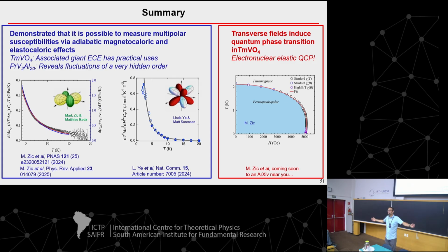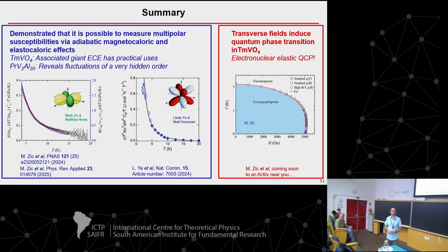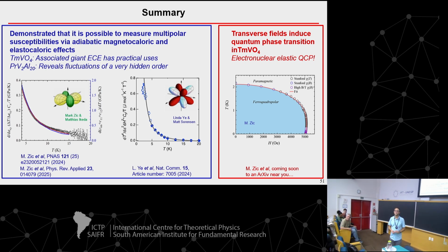Hey, Ian. There might be easier ways to do this, but I'm a neutron scatterer. If you start to polarize the nuclear spin, you will change the nuclear cross-section for neutron scattering. So you could look at diffraction peaks which had a large thulium component, and if the nuclear spin starts to polarize, you should change the nuclear intensity.